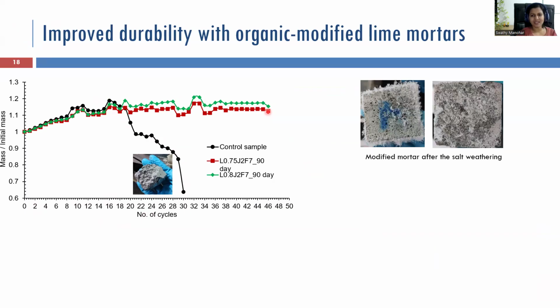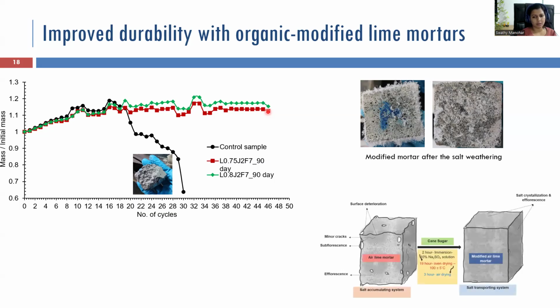Even though it was not looking great, it was having a high amount of efflorescence, which is actually not damaging to the material - it was precipitating outside the material. This probably could be because of the presence of larger pores, uniform pores, and better and uniform carbonation in the system when you have jaggery or carbohydrates within it, which is actually to be investigated more.